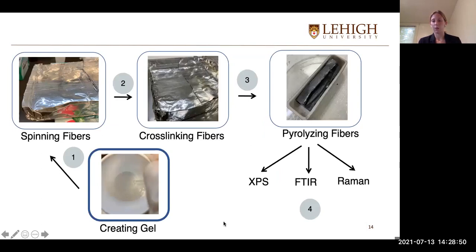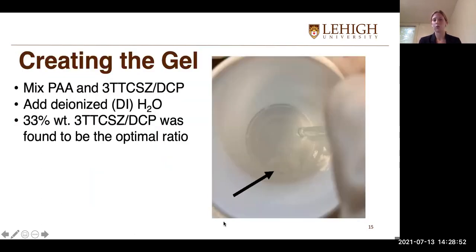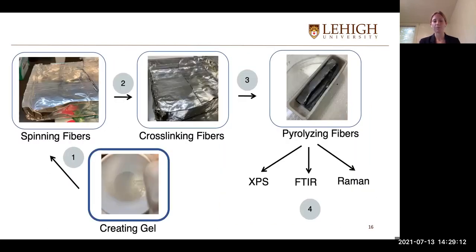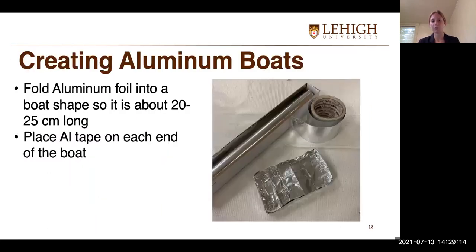And I'll start by talking about creating the gel. To create the gel, I mixed PAA and 3TTCSZ and DCP first, and then I added DI H2O. And from there, I experimented with many different weight ratios of the preceramic polymer, but I found that 33% weight ratio of it was definitely the best. So now I'll talk about spinning fibers.